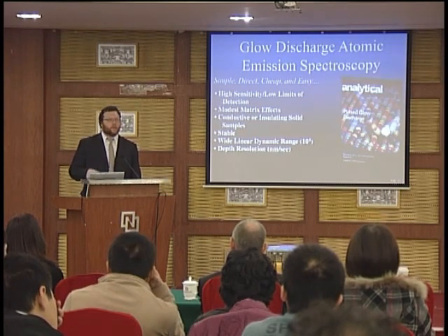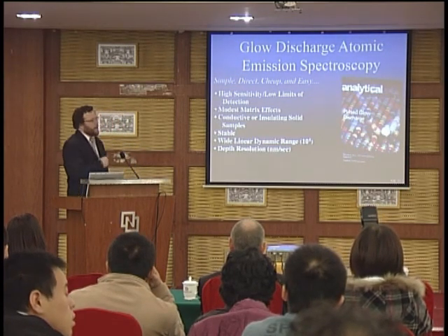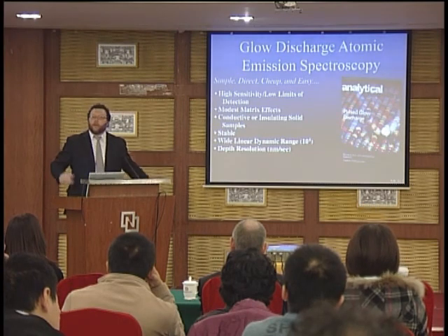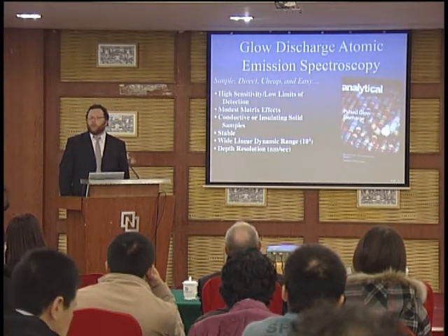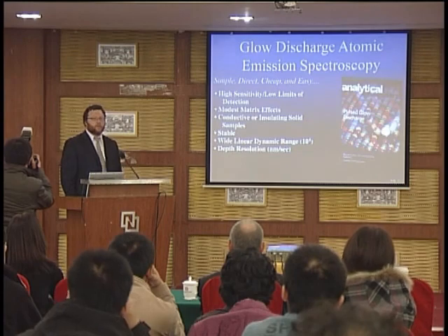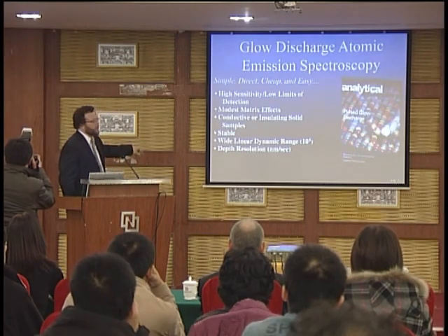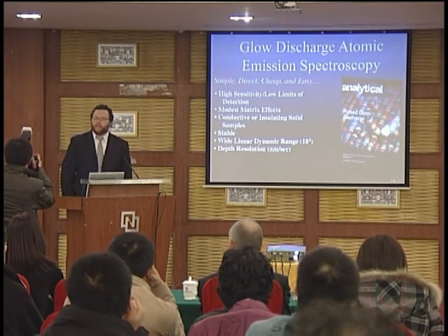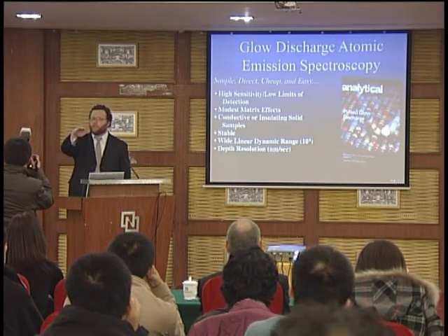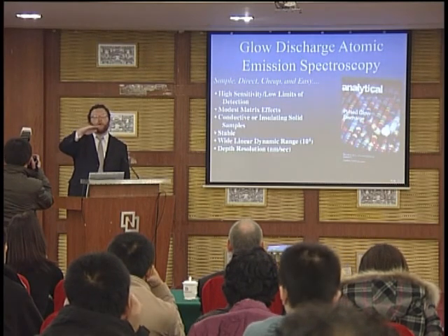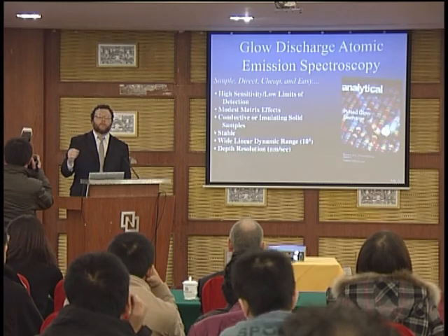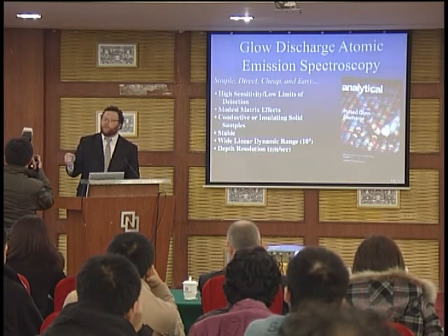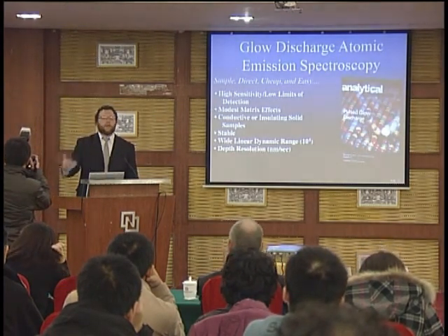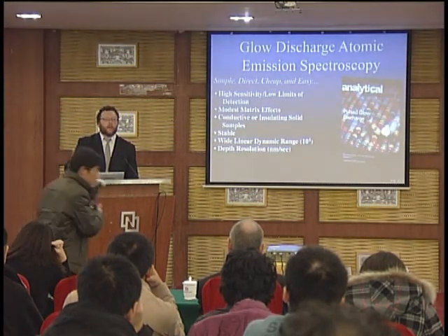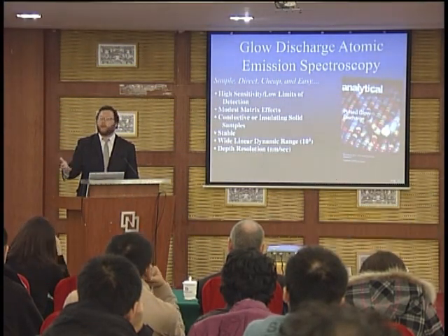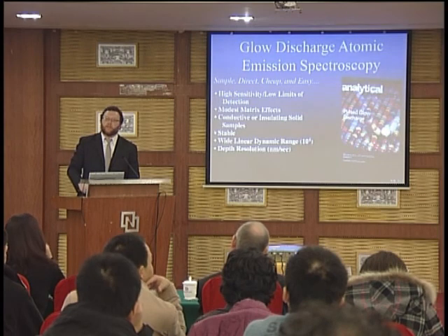And of course, in atomic terms, that means we have to think about things like high sensitivity or multi-elemental analysis, stable over a very wide dynamic range. But I'm really interested in highlighting the one at the bottom here, the idea that we can get depth resolution from the surface of the sample going down through successive layers on the order of nanometers per second, which is very important for a lot of applications in, say, the photovoltaic industry or semiconductor industry, if you're doing paint layers and things like that.